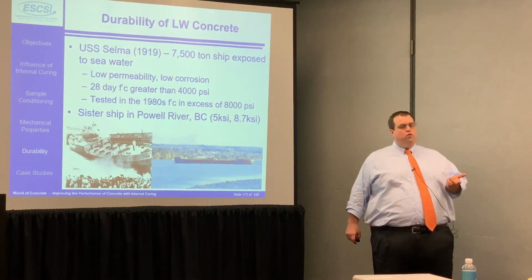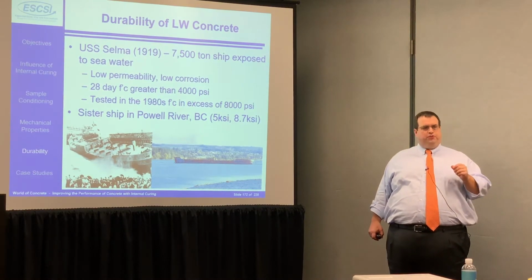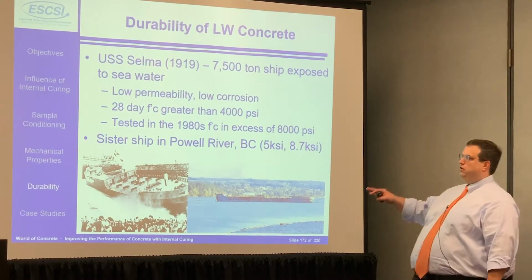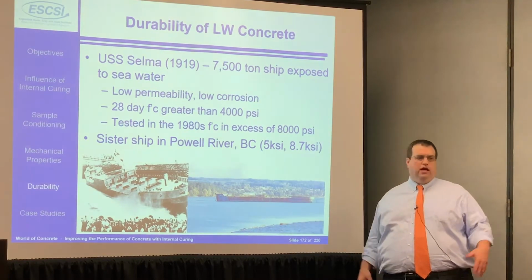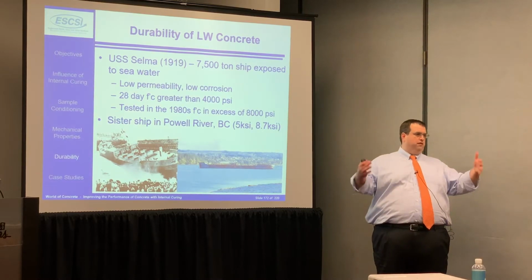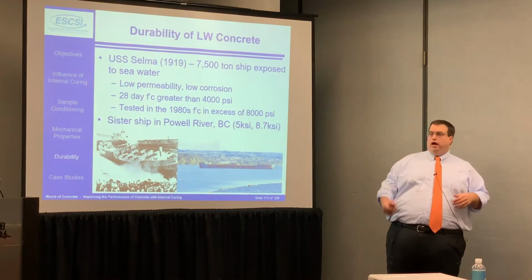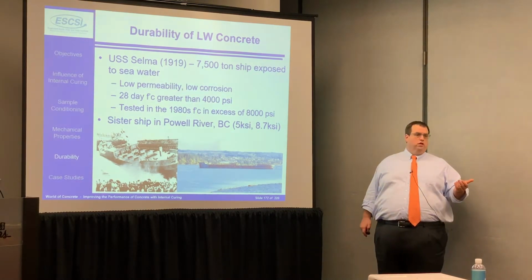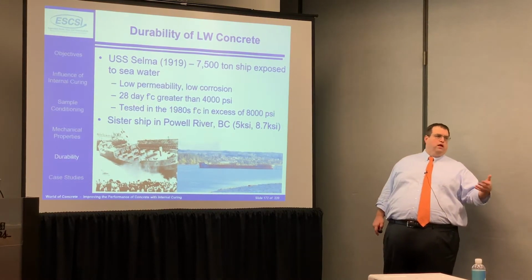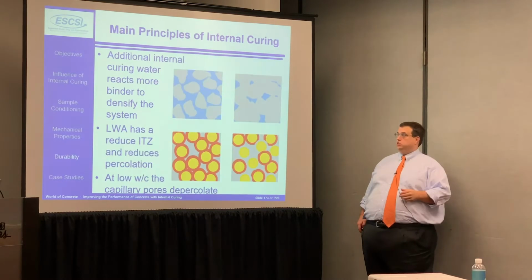Now, we know, and this is a little bit counterintuitive because the first thing people think of, there's giant pores in the aggregate, things are going to flow through there, it's going to be dogs, cats, small children going through the system. That's not what happens. All right, what we typically see is that the system is very durable. So they tested some of these big concrete, some people may or may not know this, at one time the US was building these great big ships. These ships were being used in the war effort. After they were done being used in the war effort, a lot of times they've been sunk to become reefs and become coastal barriers. Some of these have actually been cored years and years and years after exposure to seawater, and they are much less permeable than a conventional concrete.